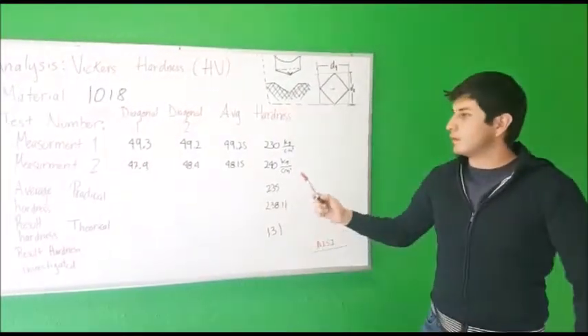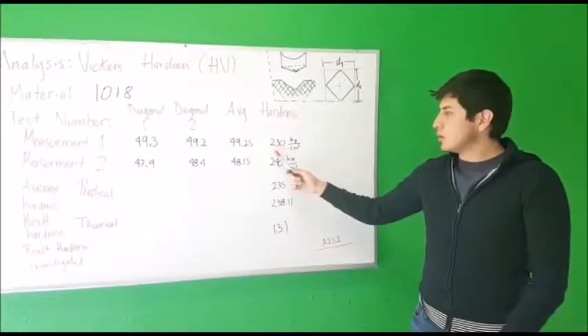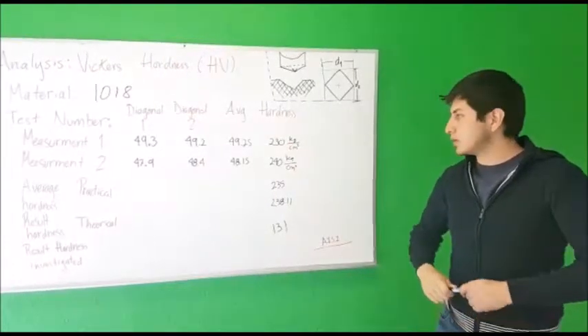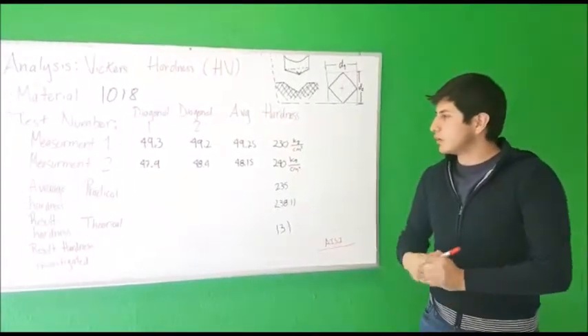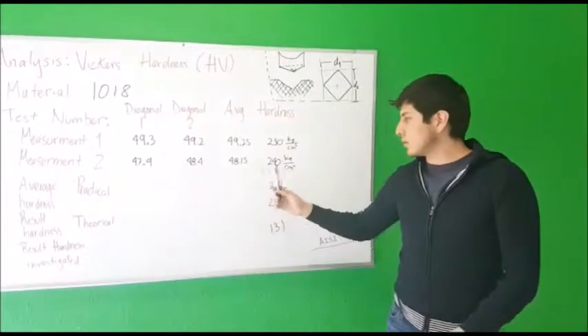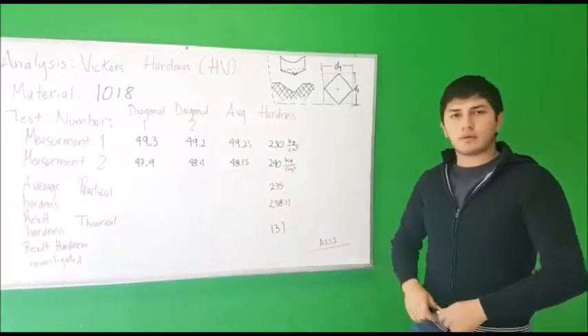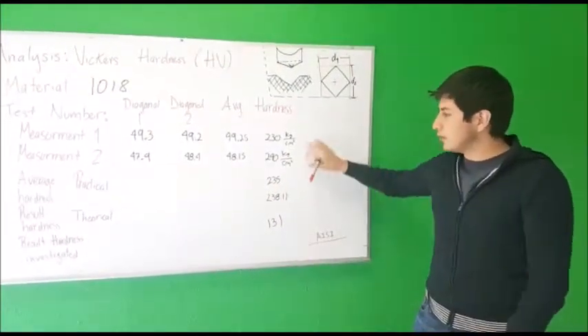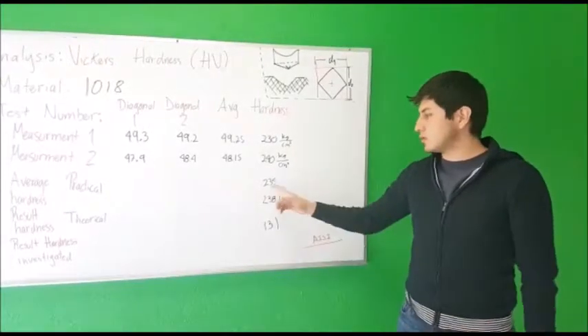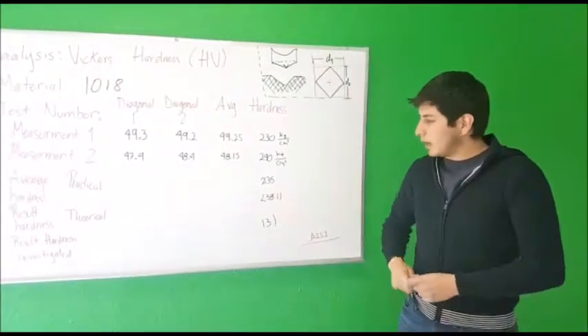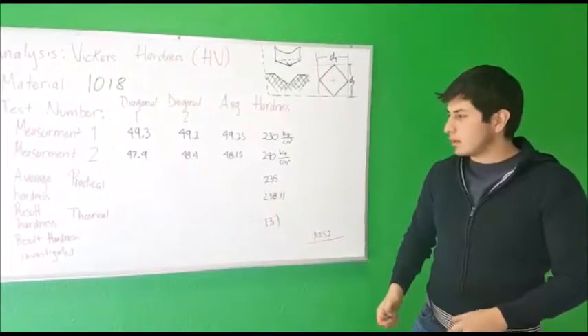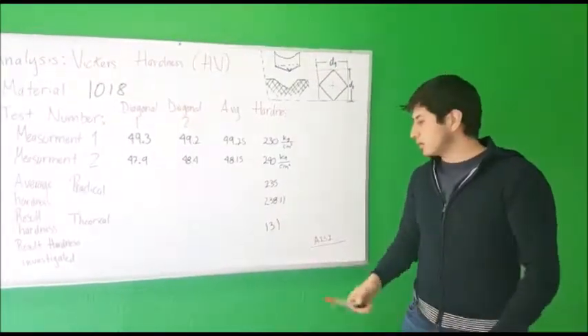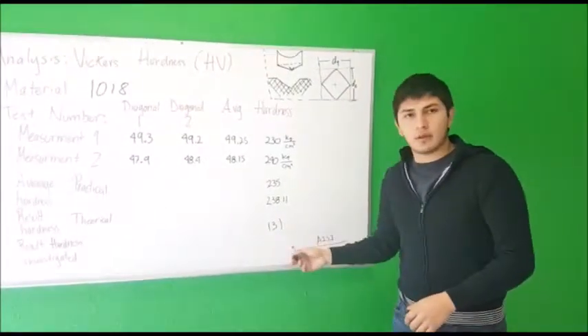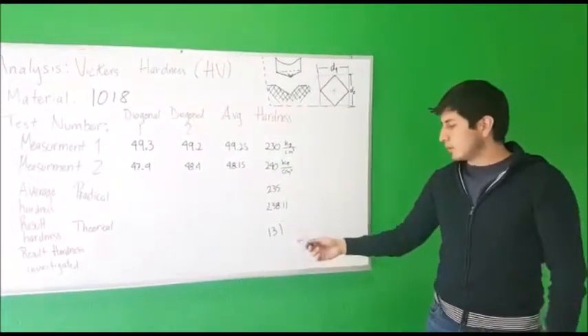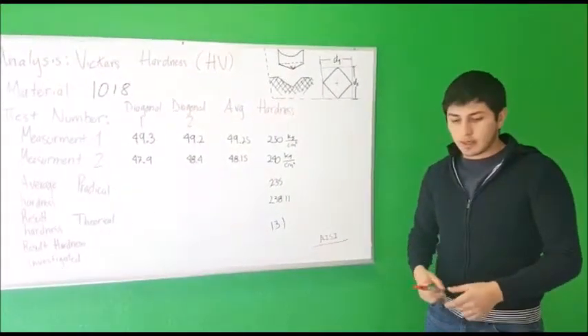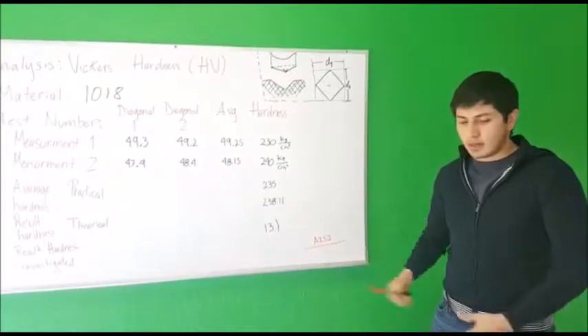In the first measure, we have 230 kilograms per square centimeter. Then in the second measure, we have 240. The average of those two is 235. Then we investigated the real hardness, which was 131. This is with reference to the American Iron and Steel.